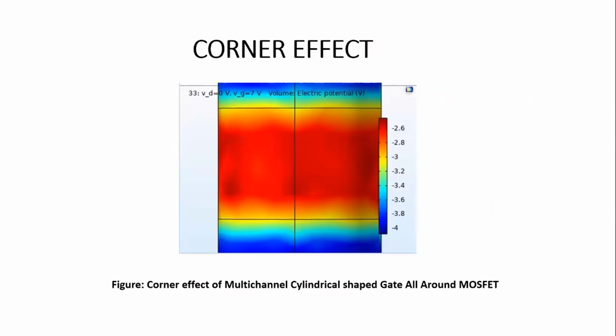Now, the corner effect. First, we should know what the corner effect is. The corner effect is known as a leakage current enhancement at the edges of the active areas in shallow trench isolated CMOS transistors. It usually deteriorates the transistor performance. Due to the symmetrical nature of our proposed device, the cylindrical shape of the gate and channel elements, the electric field, as shown in this figure, is uniformly spread in the circular rings within the channel. This provides better gate coupling, which improves the Ion/Ioff ratio of our device.